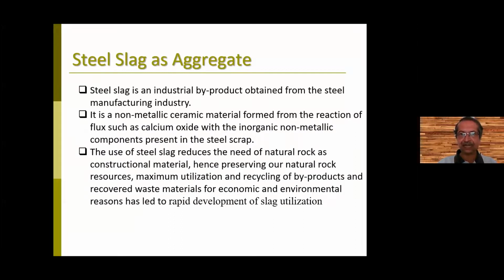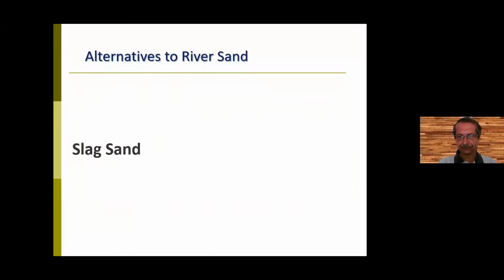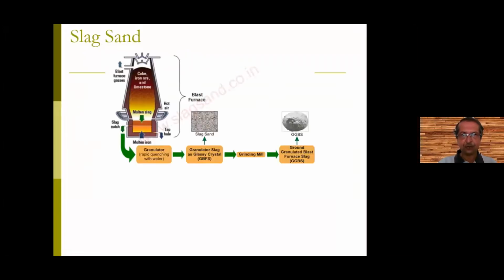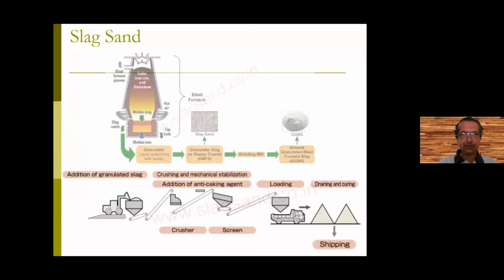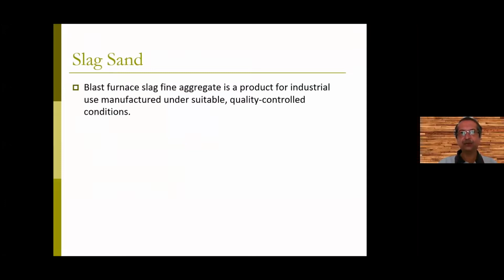So the use of steel slag reduces the need for natural rock as construction material, and hence this is being looked at. Slag sand is now being popularized. As was mentioned, this is the process of the production of the slag, and from the slag, the granulation, the granulated slag, and after grinding it, you get what is known as ground granulated blast furnace slag. So the addition of this ground granulated slag is something which should be looked at as a replacement to sand.